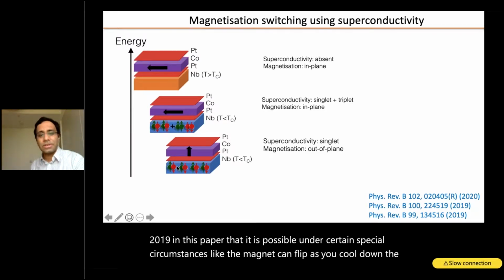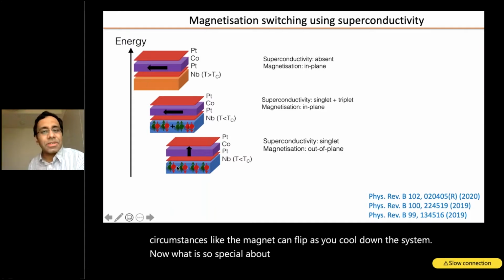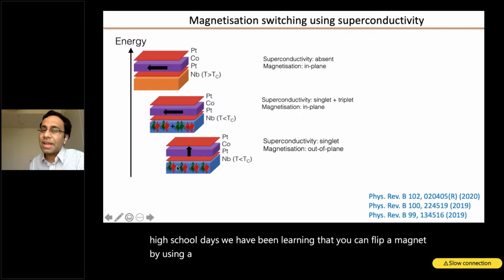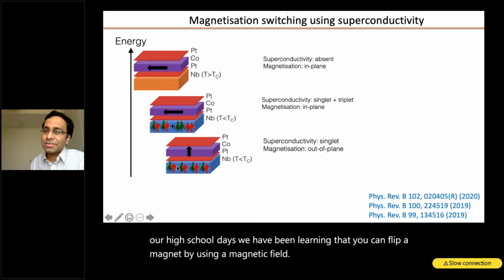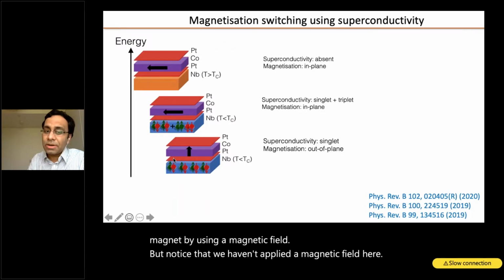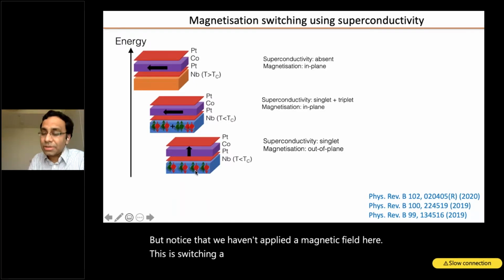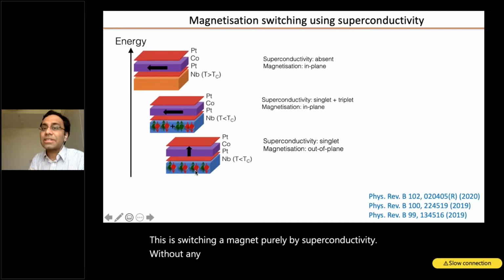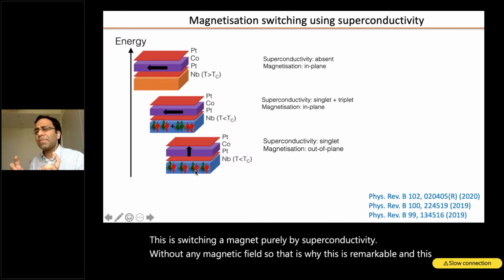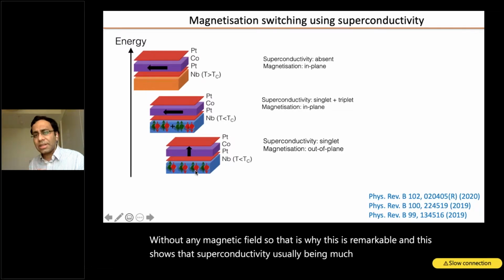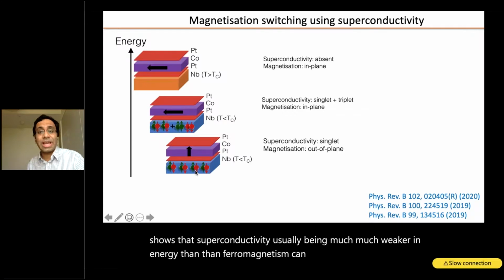Now, what is so special about this? Since our high school days, we have been learning that you can flip a magnet by using a magnetic field. But notice that we haven't applied a magnetic field here. This is switching a magnet purely by superconductivity without any magnetic field. So that is why this is remarkable. And this shows that superconductivity, usually being much, much weaker in energy than ferromagnetism, can in fact switch the magnetism, so can win over magnetism.